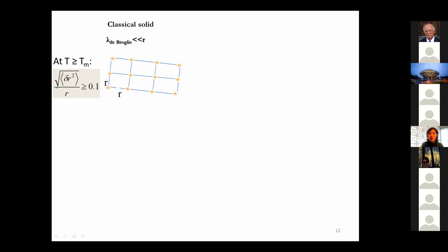And for example, if you increase the amplitude of vibrations in this type of solid, you are going to get melting. At some point, when the amplitude of this vibration becomes close to the interatomic distances, like 10% of that, the Lindemann criterion of melting, which is a very naive sort of model, it's going to cause these classical solids to melt. And most of the solids that we know of fall into this category. You can assume the nuclei are classical, the quantum effects are gone, and the amplitude of the vibrations is dominated by temperature.